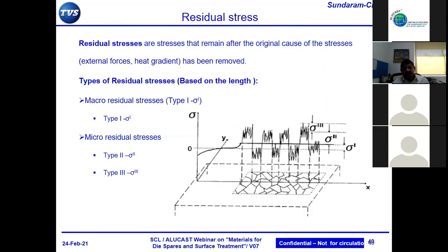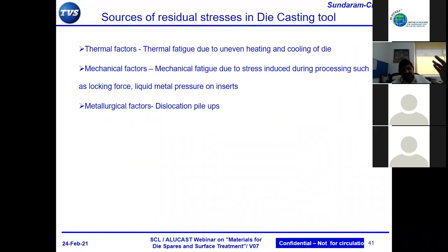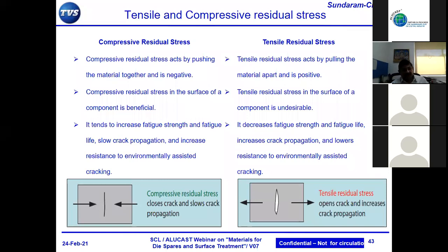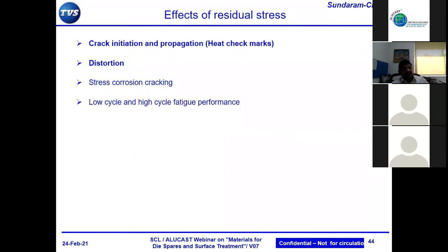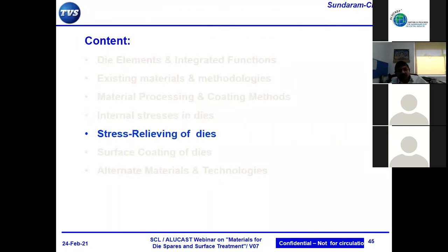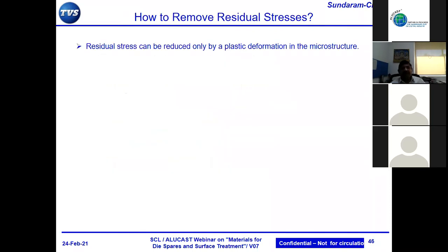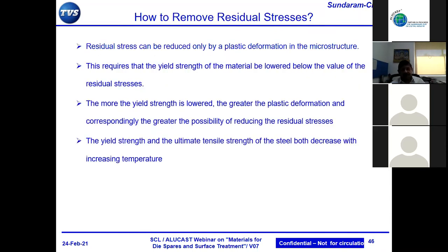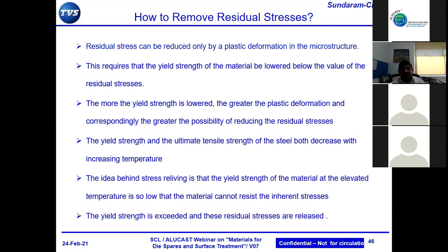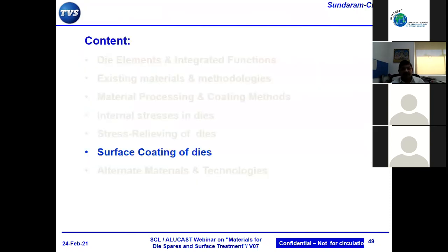So this is what I was talking about, residual stresses. Again, these are some of the things which I will not go much into details. This actually impacts the die life in terms of heat checks. And these are the mechanisms, and this is how the heat checks and the cracks initiate because of the tensile residual stresses. And this could lead to heat checks and fatigue cracks. So we need to control these residual stresses. We do a lot of heat treatment on these parts and we control the deformation, etc. So I'll not go much into the details of these.